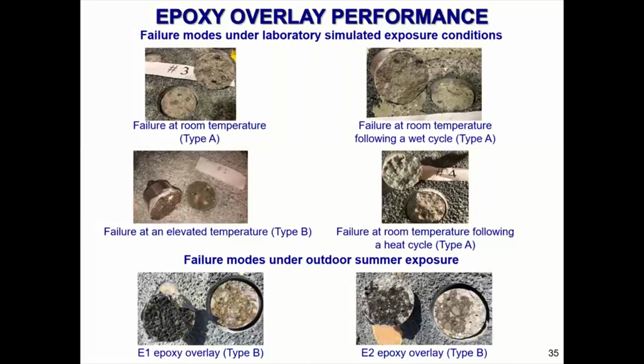You can see here some of what the failed surfaces look like. In the upper left-hand corner, failure at room temperature. You can see some aggregate exposed. You can see the failure was in the concrete. You can also see in the upper right the failure was in the concrete after the wet-dry cycle. And then in the elevated temperature, you can see the smooth surface left behind, indicating that the failed surface is the bond interface. But in the bottom middle right, you can see that after the heat cycle, that same slab, once it had cooled down, then failed in the concrete.